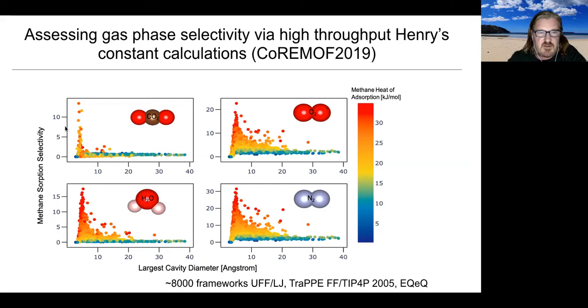We've got selectivity here, the propensity to select for methane. And on the horizontal axis, we've got the largest cavity diameter, which, as you might expect, is the largest kind of hole, but it might be something which is rather oblate, so it's the largest dimension within the structure. Broadly, the selectivity for these individual gases is rather similar. You can see for CO2, we require very small cavities within the structure in order to discriminate for the methane.